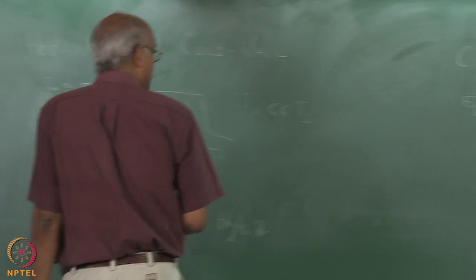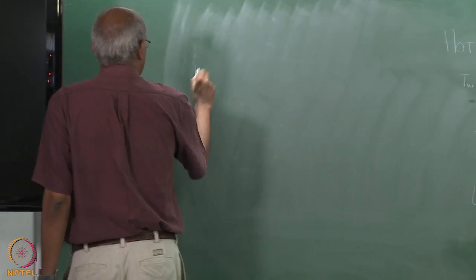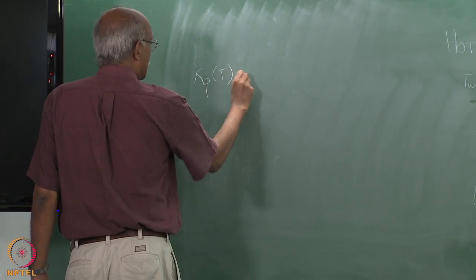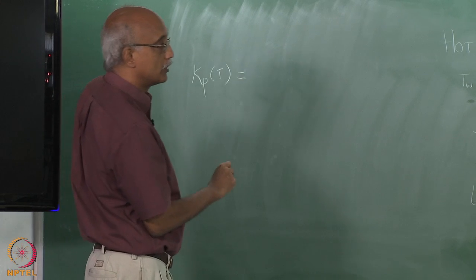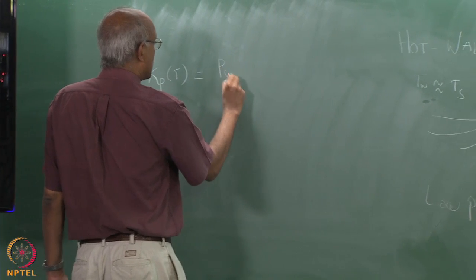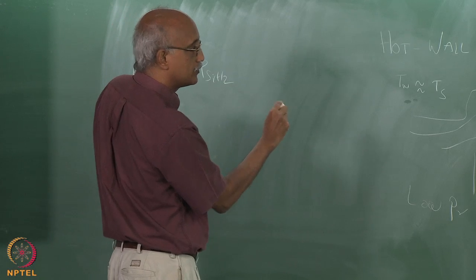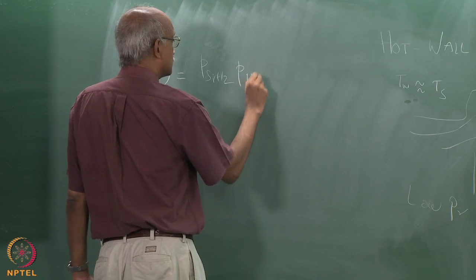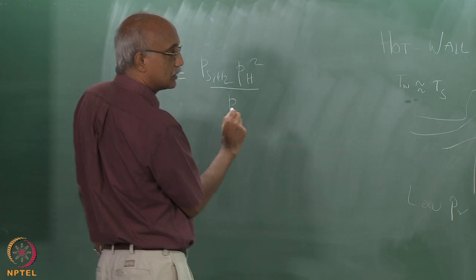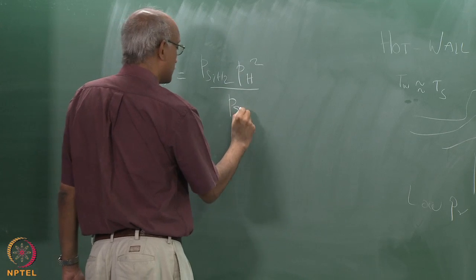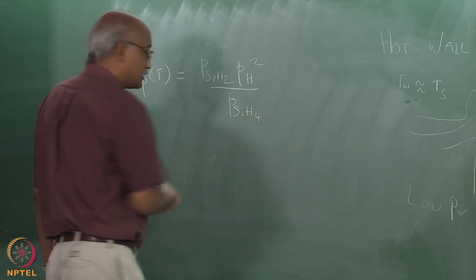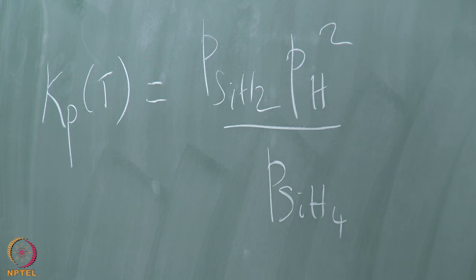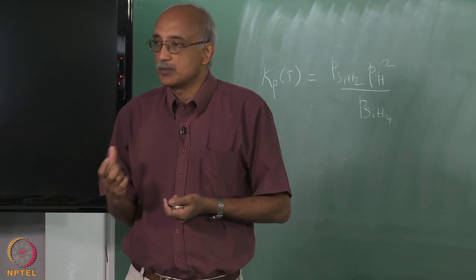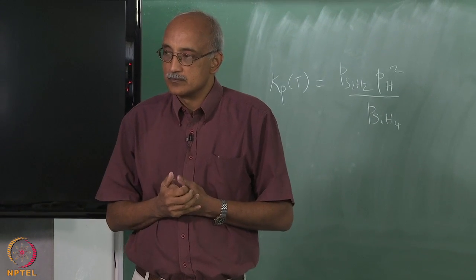So, you can write some Kp, a function of temperature, equals P SiH2 times P H2 squared over P SiH4, where this Kp you can write as some Kp0 exponential of minus delta G by kT. So, you can actually calculate the rate constant from the thermodynamic properties of the reacting species.